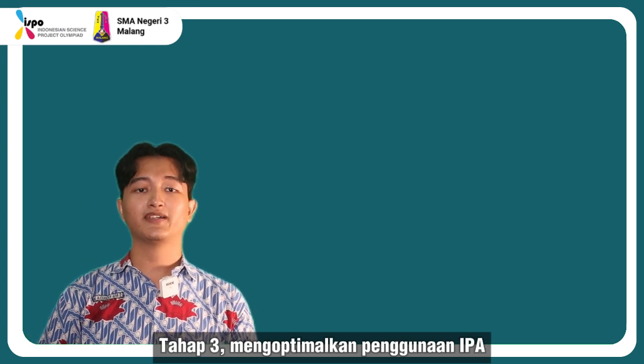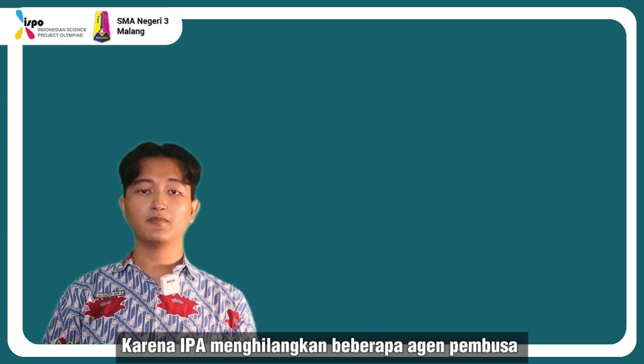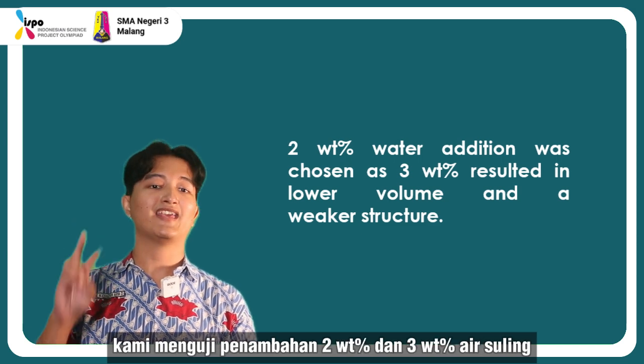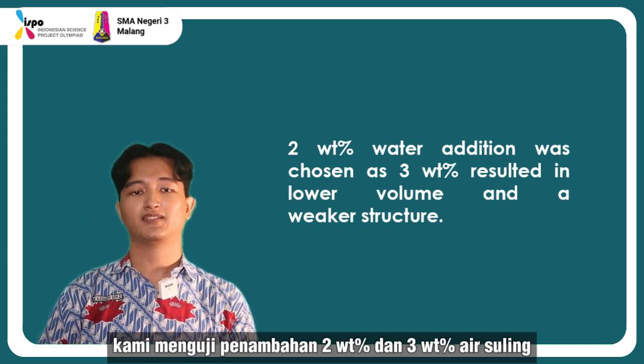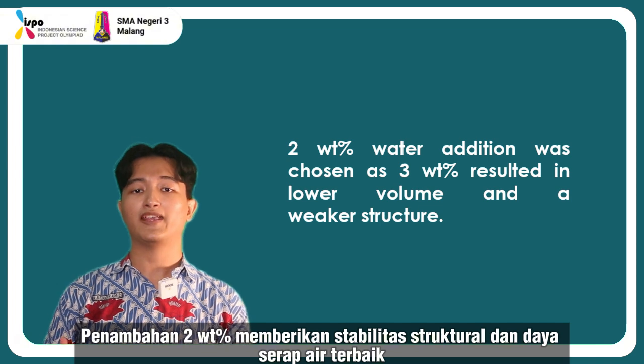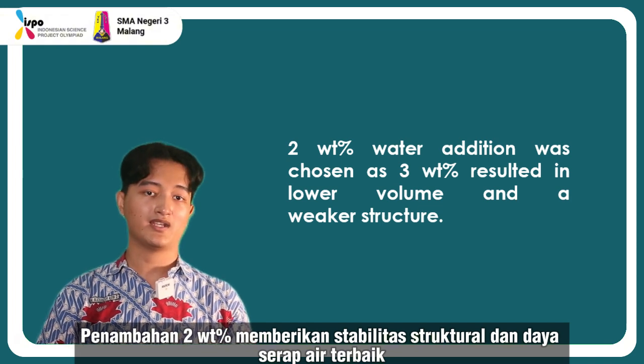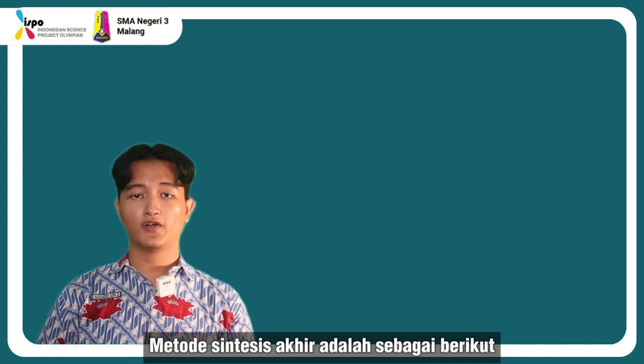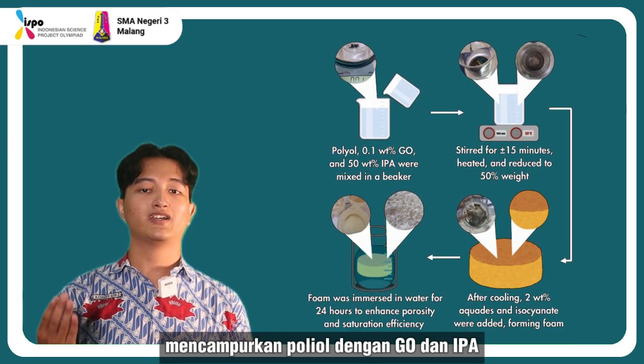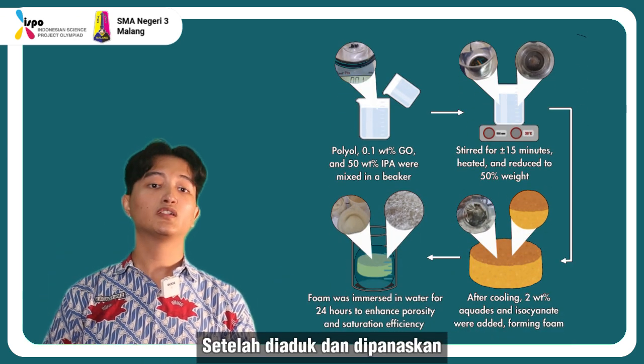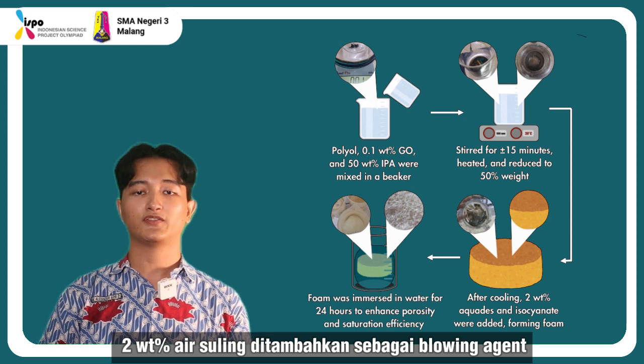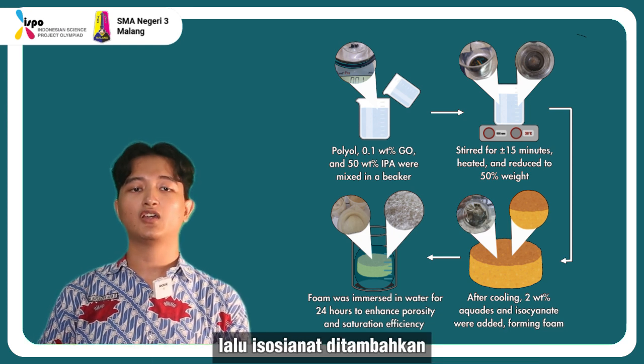Step 3, optimizing IPA use. Since IPA removes some blowing agents, 2 weight% and 3 weight% distilled water was tested. The 2 weight% addition proved best for structural stability and water absorption. The final synthesis method is as follows. Mixing polyol with GO and IPA. After stirring and heating, 2 weight% distilled water was added for blowing agent, followed by the addition of isocyanate.